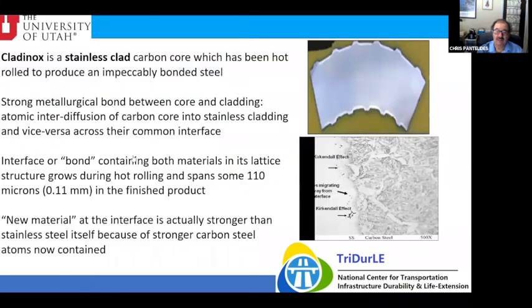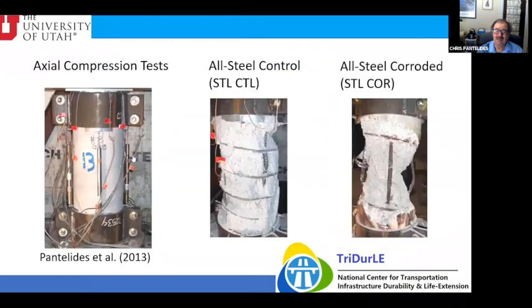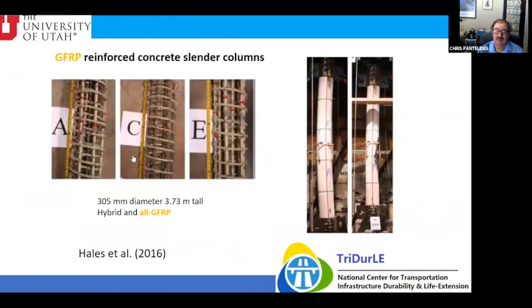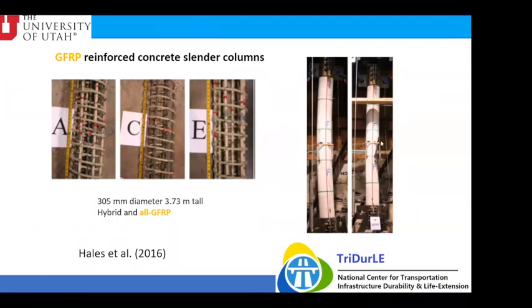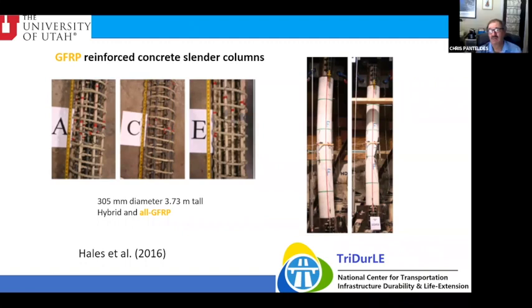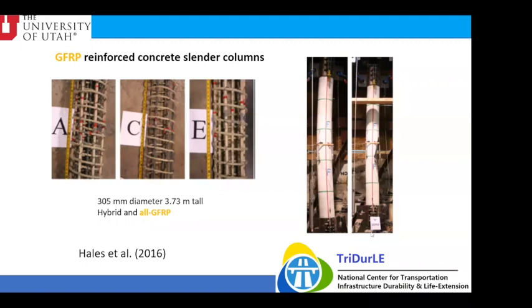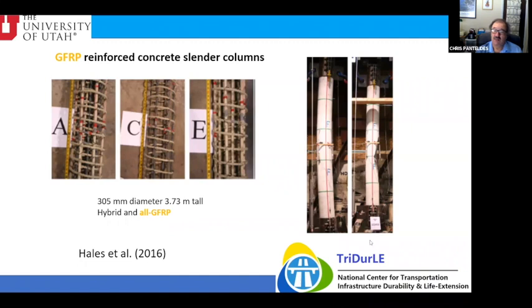For example, in this test of a slender column, you can see here on the right, this is right about to fail. And of course, the way it fails, you get compression here, failure of the concrete. But the reason I put this picture here is after it buckled, a very nice sine wave, we removed the axial load. And guess what happened? The column came back to vertical because the material is elastic. The fiberglass wanted to go back to its zero position, right? And so it's kind of a self-centering mechanism if you have fiberglass bars.